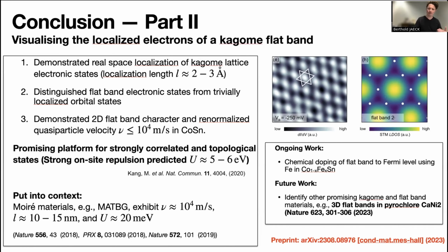However, what distinguishes both materials is that, for example, in twisted bilayer graphene, we have a relatively large localized state length scale of above 10 nanometers, which then maps to a relatively reduced on-site Coulomb repulsion. While, of course, the control and realization of these Kagome metals is more challenging, this very strong localization at the atomic scale, combined with the d-orbital nature, is predicted to result in relatively large on-site Coulomb repulsion terms. In other words, if we are able to tune this very flat band with very localized charge carriers to the Fermi energy, there is reasonable hope to find strongly correlated states once we're able to partially occupy these flat bands.